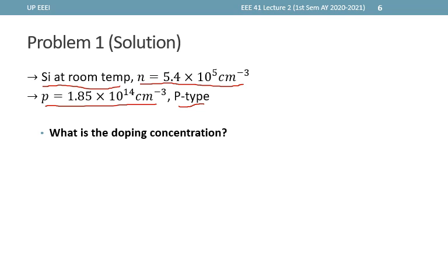So going back, we have identified some quite long formulas relating the carrier concentration to the doping concentration. So n is equal to (Nd minus Na) over 2 plus the square root of ((Nd minus Na) over 2) squared plus Ni squared. However, there are simplifications for p-type where p is approximately Na.